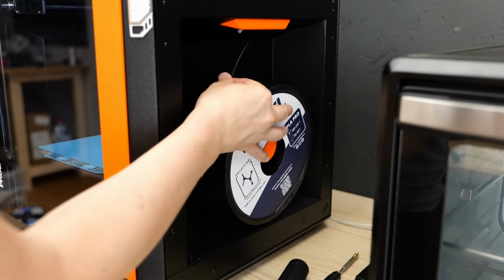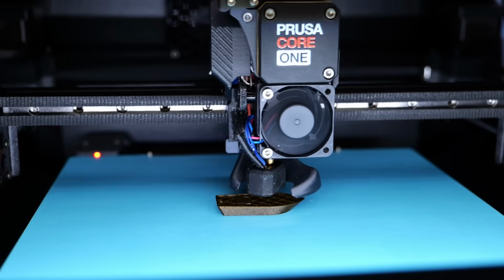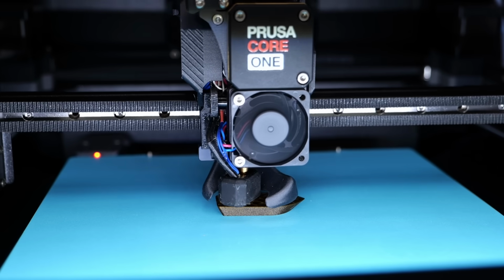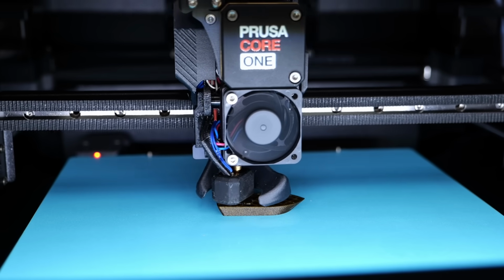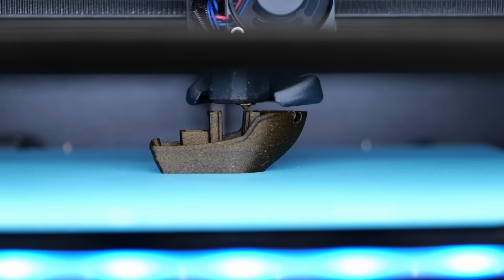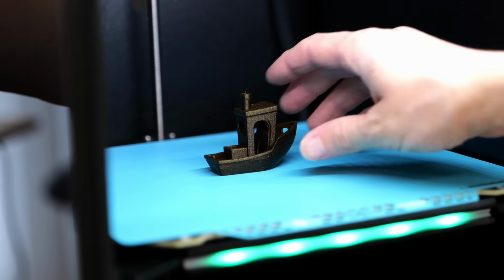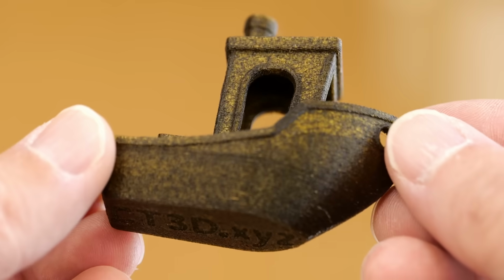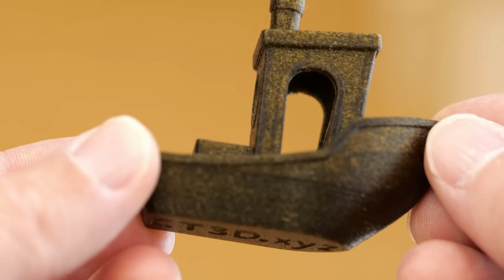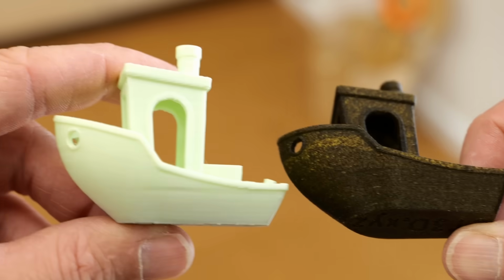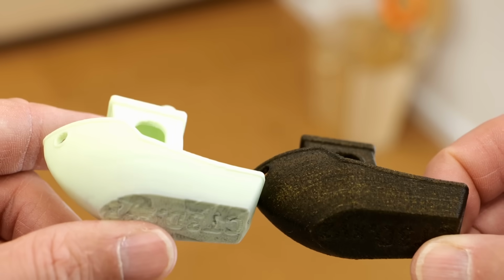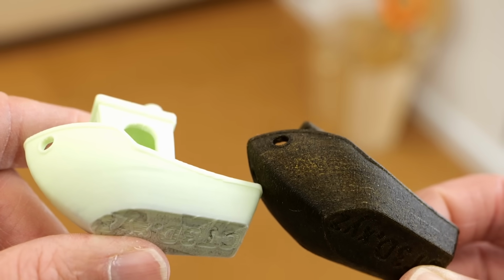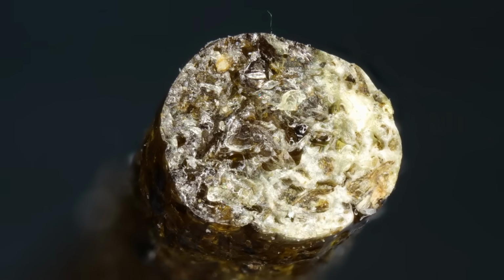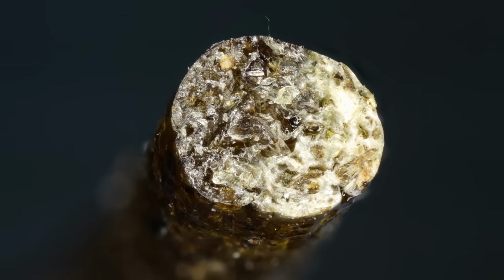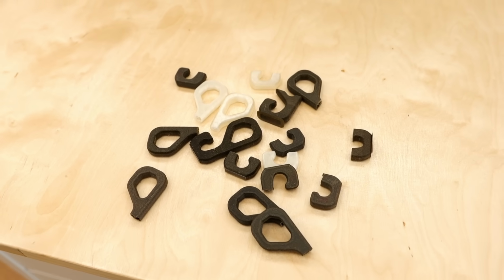Since the filament looked so uniform, I thought I'd go all the way and print a 3D Benchy with it using a standard 0.4mm nozzle. And this, to my surprise, worked remarkably well. The filament printed without any problems and at an amazing level of quality. You could even argue that you were able to see the reinforcement effect, because I was missing the typical bowline that results from the shrinkage of the material during printing. We'll see if the fibers really reinforce the material when we later test and compare its strength.